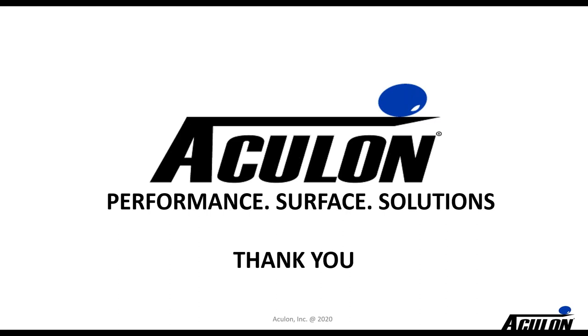Okay. There's a question. Does the coating have good impact resistance? We have a pretty broad variety of coatings. So for certain things like treatments on metal, as I say, we're as good as the underlying substrate. So if you damage or tear away the underlying substrate, then you're basically going to be tearing away the treatment. I mean, those are less than 5 nanometers thick, so they're not adding to impact resistance, but they are very, very good. They're not brittle. They don't crack. They don't flake. So again, it's going to depend a little bit on the substrate, but you're as good as the underlying substrate.